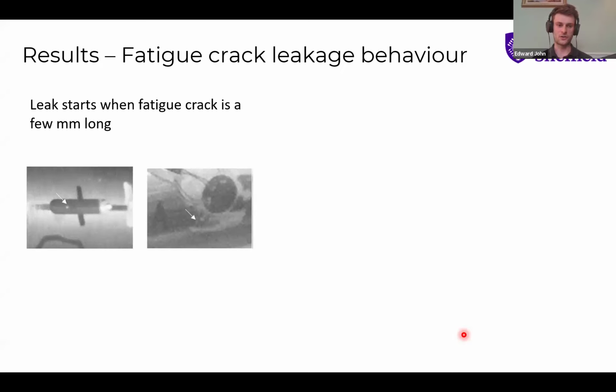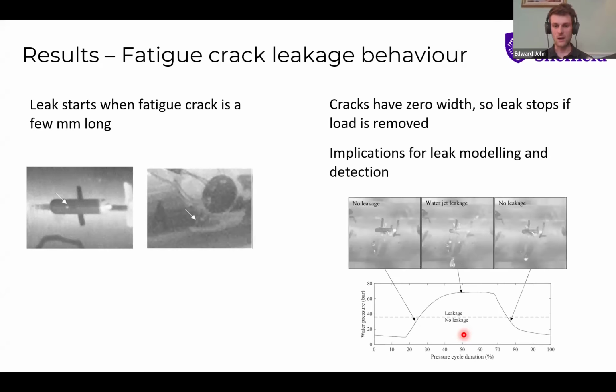So I think the first thing that's of interest is that the leak can start when the fatigue crack itself is only a few millimeters long. So basically very, very small cracks can cause leakage, although clearly this is very small and probably undetectable. But it's important to understand that as soon as we have a crack that spans the pipe wall, we begin to see some kind of water loss.